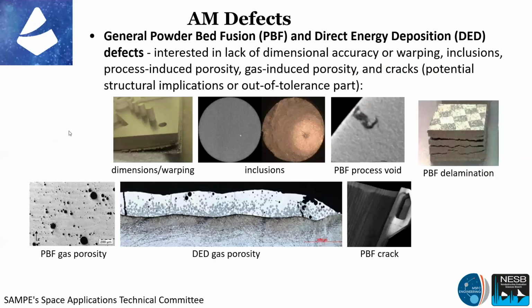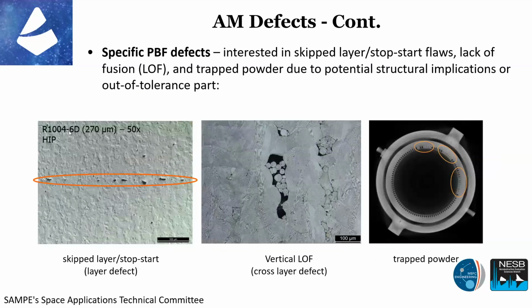So just for completeness and background, for those of you who aren't deeply involved with additive manufacturing, there's a lot of different defects that can happen as you're building these things up. You can certainly get dimensional warping, inclusions, because you're building layer by layer. This is a powder process fusion void. You can get delaminations, gas porosity, direct energy deposition gas porosity, and certainly residual stress cracks that form in the powder bed fusion parts as well.